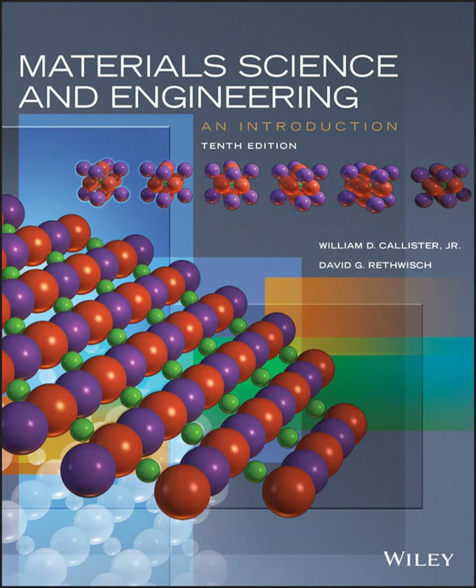There's intergranular corrosion. This is selective attack right along the grain boundaries of the metal. The grains themselves might be fine, but the boundaries corrode. This is a major issue in some stainless steels if they've been heated improperly, say during welding. This heating can cause chromium carbide particles to precipitate along the grain boundaries. This depletes the chromium right next to the boundary, making those narrow zones susceptible to corrosion, almost like tiny galvanic cells are set up. It's often called weld decay.